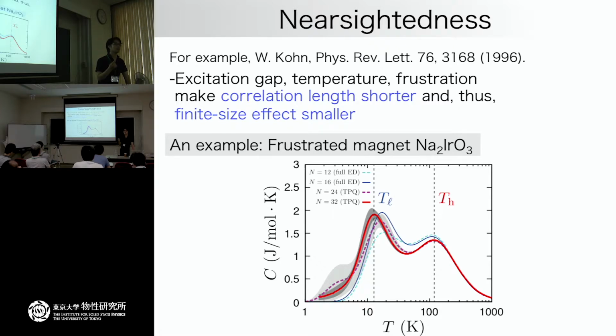Okay, so maybe we should discuss in a much more quantitative fashion. But if we talk about temperatures higher than 0.1, it's going to be fine. Almost all the sizes will lie on the same curve. Because if you go down below 0.1 J, not Kelvin, I think it's going to be. Yeah, because in the Kagome lattice case, the heat capacity has more or less a single peak and a shoulder, and the peak temperature is more or less fixed. Oh, it's true, but if you do it with 30 something, it's a bit different. The remaining low temperature entropy is not so large. Well, compared to triangular, it's still large. Compared to triangular, yes, but the point here is that we have a large entropy remaining around this temperature, more than half in this system.